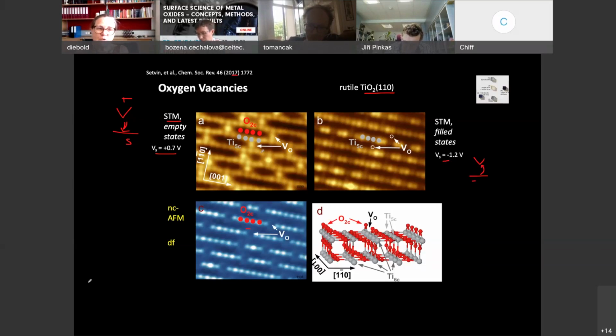And then we see different things. This is exactly the same area on the sample. We have these rows of oxygens, we have these rows of titanium in between, and we have these oxygen vacancies. In empty states, when we tunnel from the tip to the sample and stuff electrons in, there are no states available in the empty states. You can see here is an oxygen vacancy. We see a bright spot. The reason is just that the empty states, the unfilled states, have changed a little bit. The orbitals have changed a little bit, but it's not really an atom here. It's just a change in electronic structure.